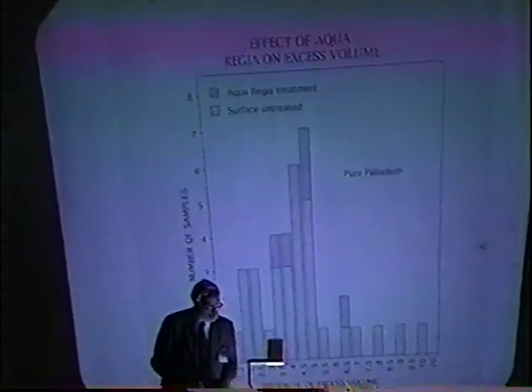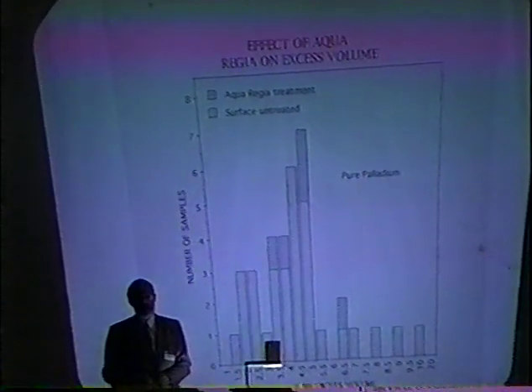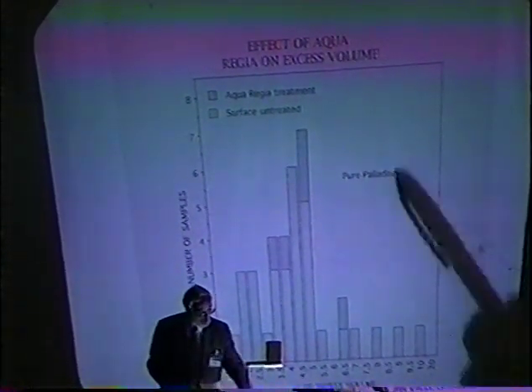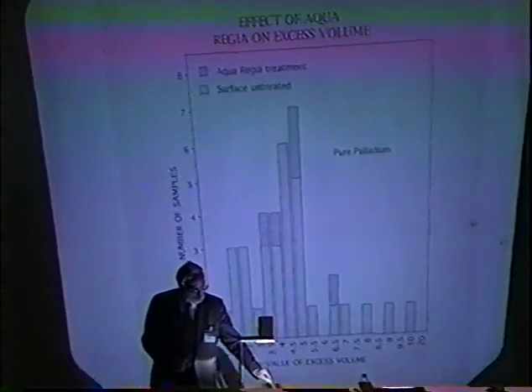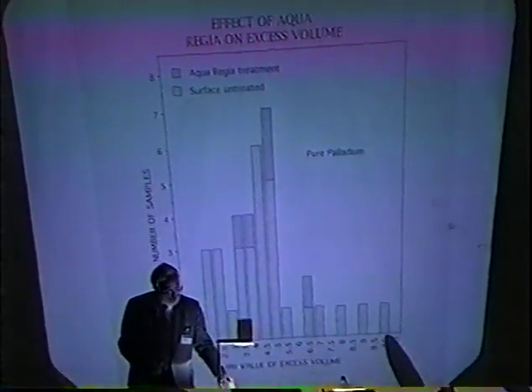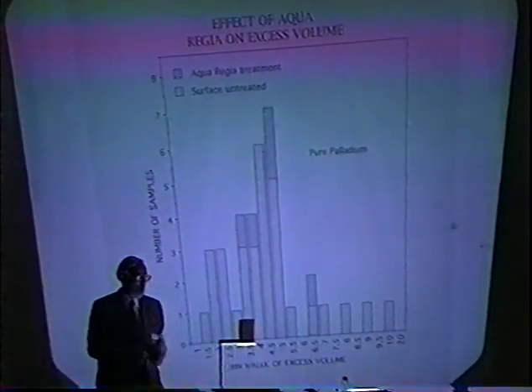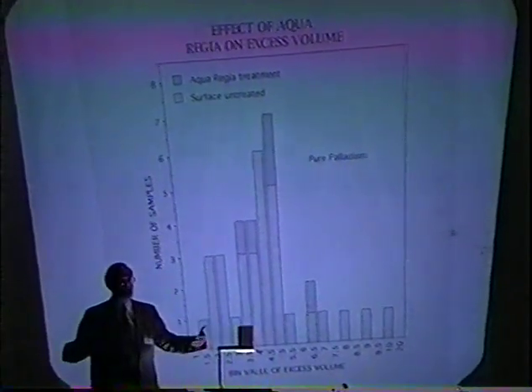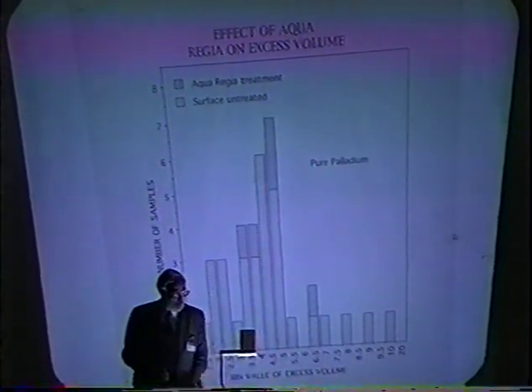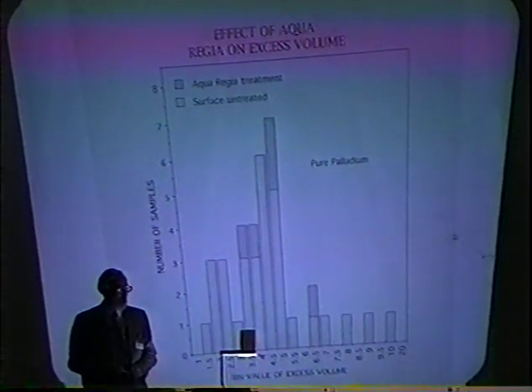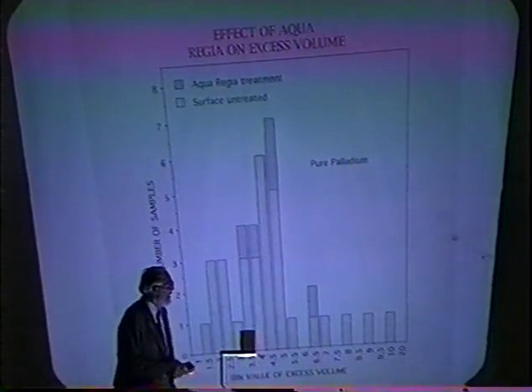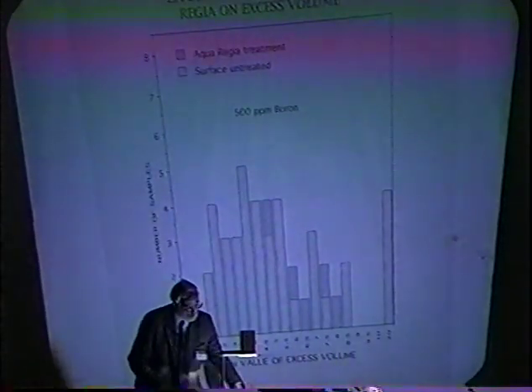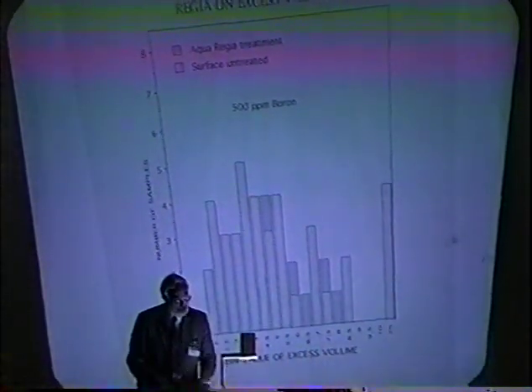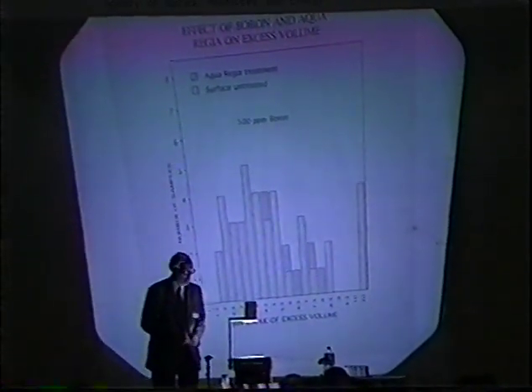The same can be said of the excess volume. The excess volume also has a range of values. This is pure palladium, and you see it goes from 1.5% up to 10%, for no apparent reason. I mean, many of these samples were from the same piece, adjacent to one another on the strip of palladium that was being made. So there's no reason why we would expect it to be different, but it is. If, on the other hand, you look at the boron, it shifts it up and makes a lot of material that has a very high excess volume. In other words, boron is undesirable from that point of view.